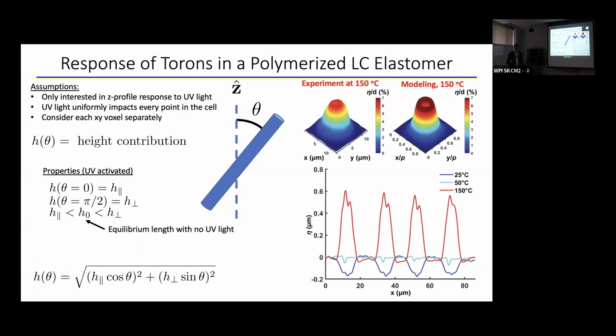And you can easily understand it by just imagining rods, right, which point in a certain direction. And then as you disorder them more, they will point more to the directions orthogonal to that original direction. So when the molecules are cross-linked, that results in contraction along the director and expansion in directions perpendicular to liquid crystal director. And that can be easily captured by some coefficients of expansion at different temperature, which are large because we can have 300% strain just by changing temperature. You could see the response was very dramatic.